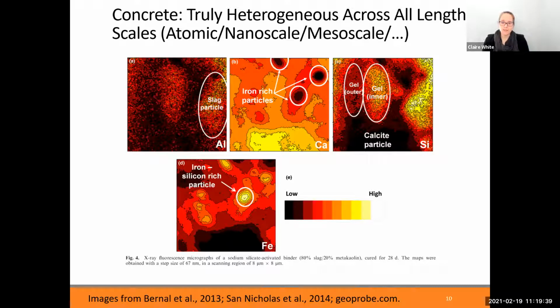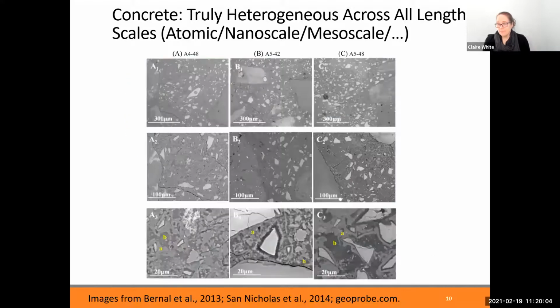And so this is, if we've got an 8 micron size box, this is 8 microns. This is an alkali-activated slag where there's some gel that's forming with different compositions. There's a calcite particle. If we look down here in this region, which is over here, there's an iron silicon rich particle from the unreacted slag. There's another piece of slag over here as well. So that's at the micron length scale.